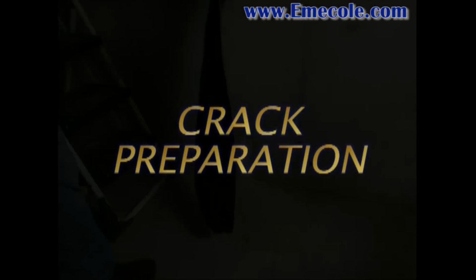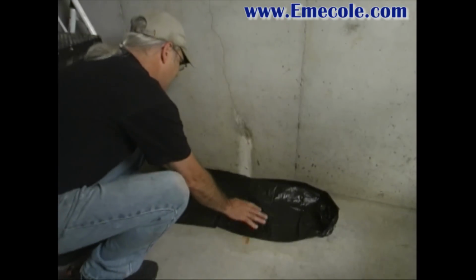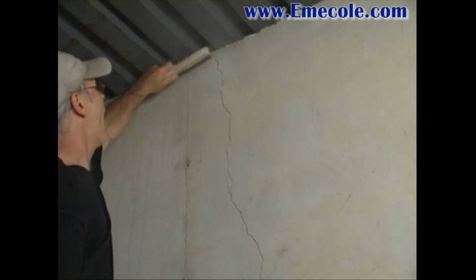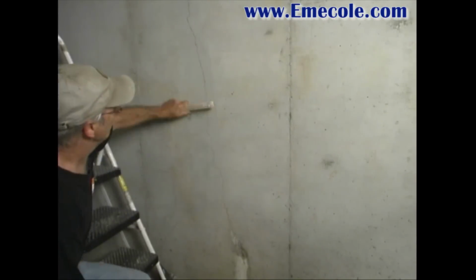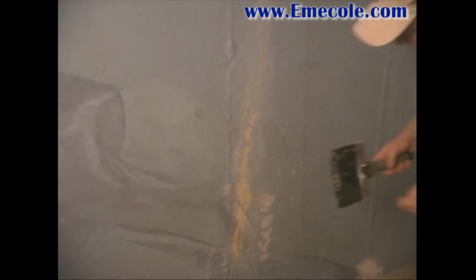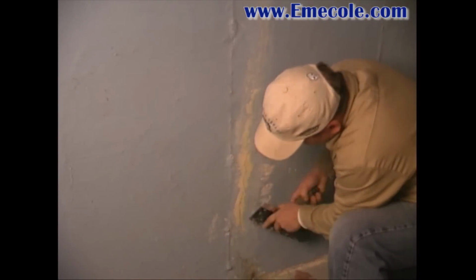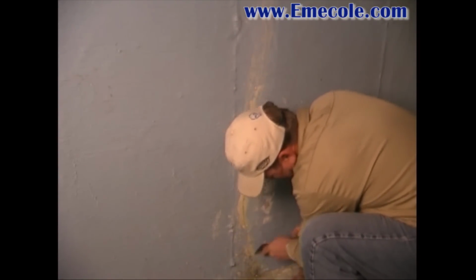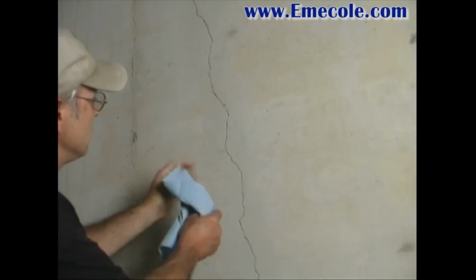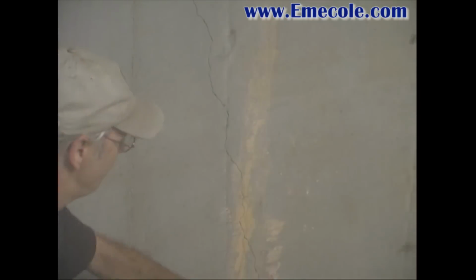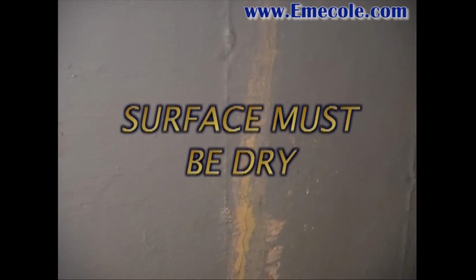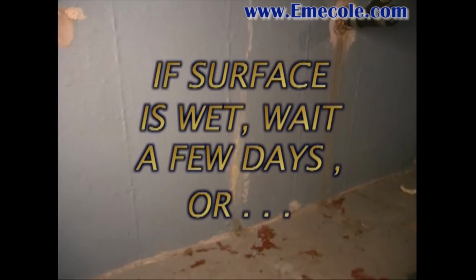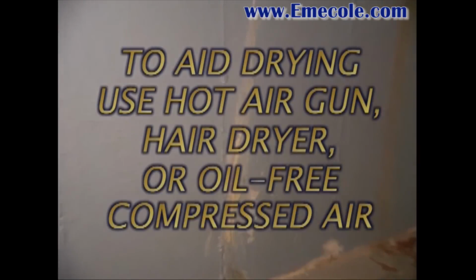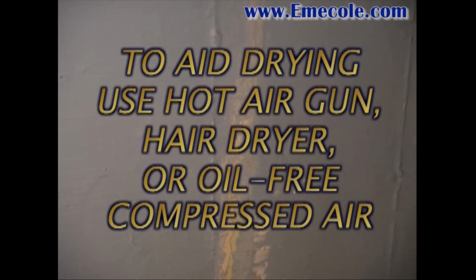Crack preparation. Place the drop cloth on the floor in front of the work area. Clean the surface surrounding the crack using a wire brush. Remove loose or flaking concrete, efflorescence, paint, or coatings to approximately 1 to 2 inches on either side of the crack. Wipe the surface clean of dust and debris. The surface must be dry for proper installation of injection ports and surface seal. For best results, if the surface is wet, wait a few days until dry, or if necessary, use a hot air gun, hair dryer, or oil-free compressed air to dry the wall.